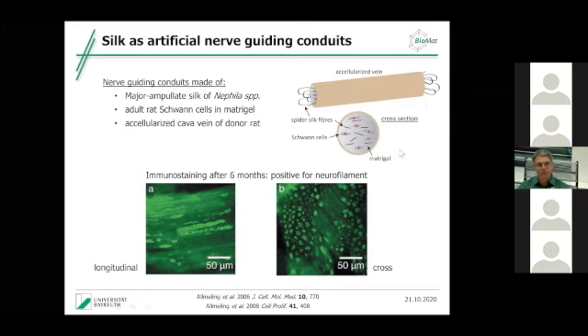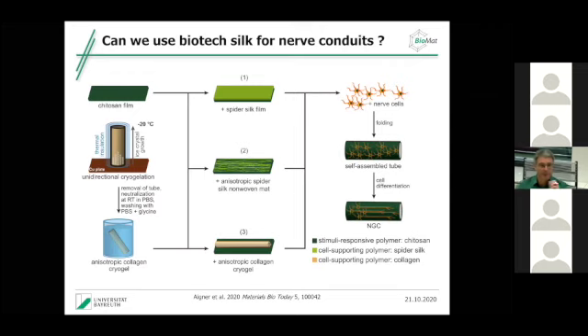We want to have a very rapid technology that allows us to actually get the nerve back to function quite quickly. And for that, we thought about self-rolling systems. So if you combine spider silk with chitosan, you have a 2-layer system that is responsive to liquids, because if you now add cell culture medium, the chitosan will expand differently than the spider silk film, and you will get a self-rolling. So you actually can create out of a flat film a tube.